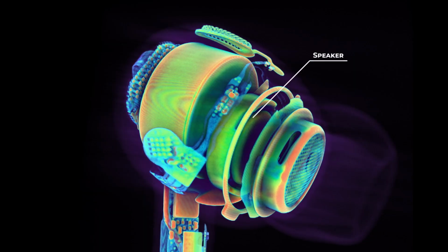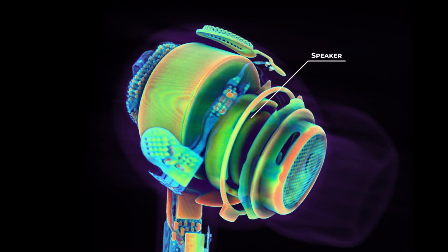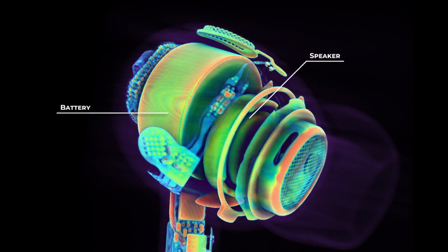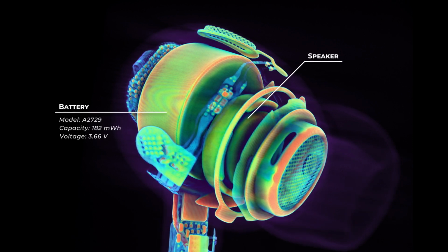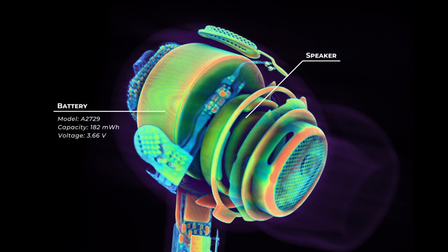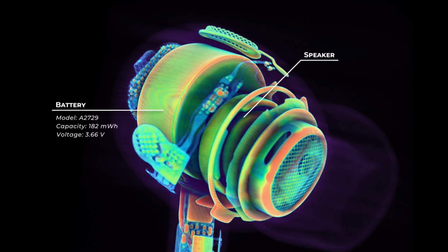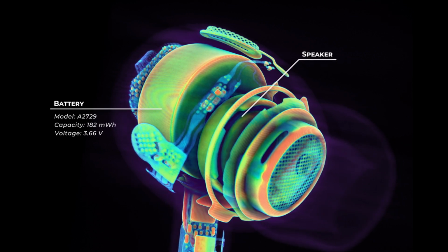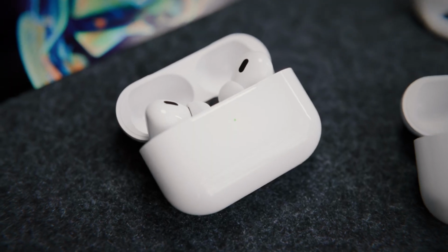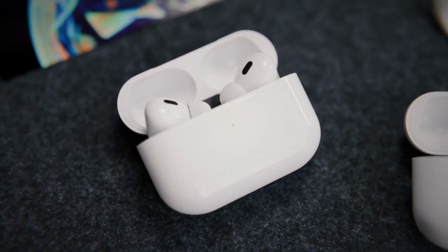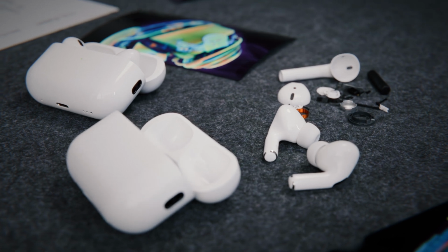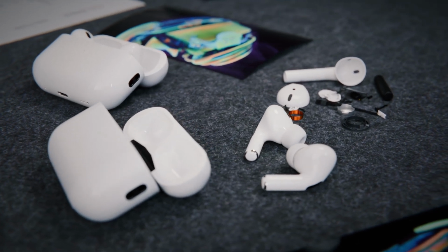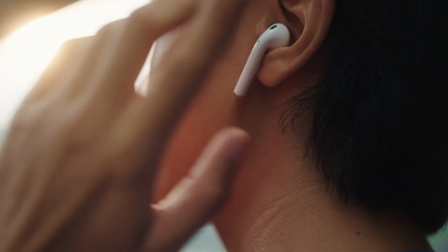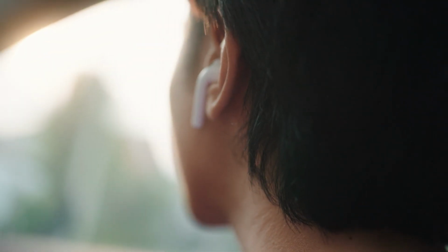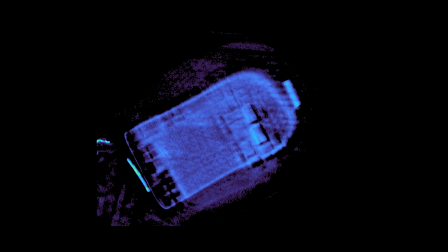Up here at the top, you can see the speaker, tucked into the part that sits right inside your ear. Right behind the speaker is a small cylindrical cell. This is a 182 mWh lithium-ion battery, about 2% of the battery capacity of an iPhone. The crazy thing is, that was enough to give each AirPod up to 6 hours of use. That 182 mWh is held in a battery that weighs just 3 grams, which works out to around 60 watt-hours per kilogram. Not particularly impressive, but Apple's consistency in manufacturing really shows up under these CT scans.